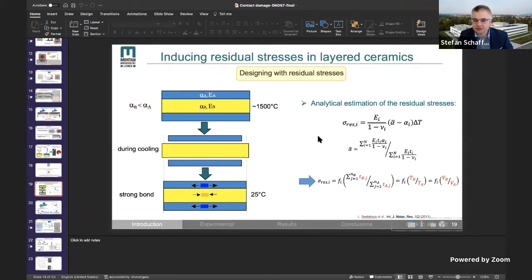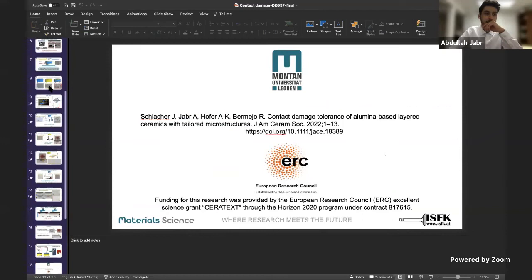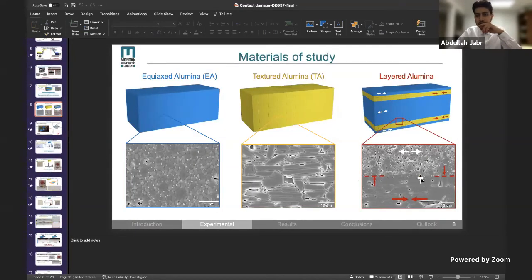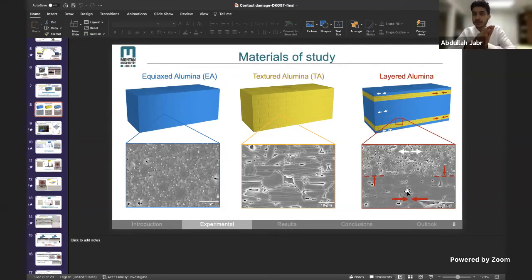Further questions from the audience. Question: You're saying that the surface has a higher thermal expansion than the body in the middle — so you don't see any delamination? No, because both layers are strongly bonded, as we saw in SEM. You have a really strong interface, and this is what gives rise to our residual stresses. There are no delaminations, and this is the interface between equiaxed alumina and our textured alumina material. To ensure this strong interface, we co-sintered the materials together, which were produced by tape casting — tape cast layers that were pressed together and co-sintered.